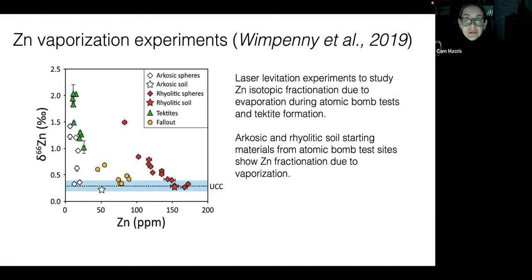They used two different starting materials. They used an arkosic soil and a rhyolitic soil. And here those experiments are plotted together, also with tektites shown as these green symbols here, and also the trinitite, nuclear testing fallout glass. And you can see that all appear to fractionate zinc isotopes with progressive zinc loss, just as we saw for copper.